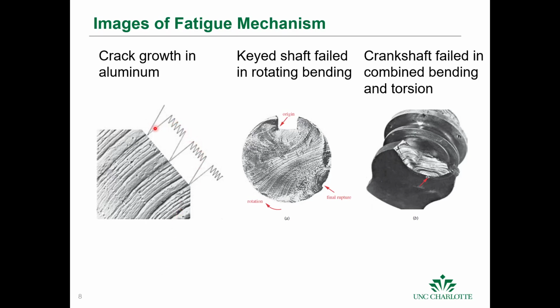If we zoom in on a material that has been fatigued, we can see these little beach mark patterns. You have a crack, and that crack is subjected to cyclical stress, and it propagates along the surface with those cycles of stress, slowly and slowly, until you get failure. You can see here the origin of a crack, and it just moved all through the surface. This is a keyed shaft in rotating bending. You can see how these lines move across the surface until you finally have a small area where your stress intensity is equal to your fracture toughness, and the material ruptures.